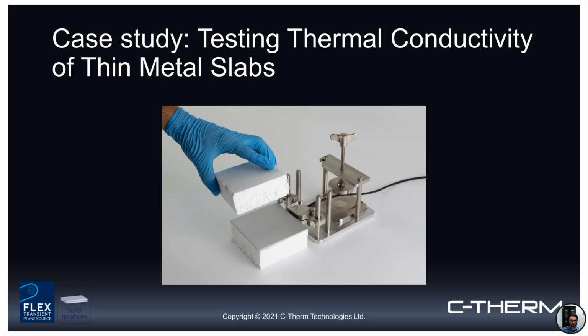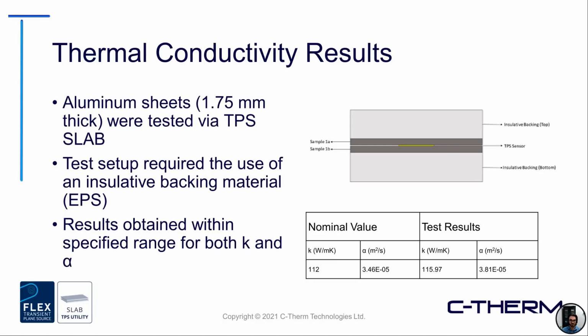And another note on one of the other advanced utilities with TPS is looking at SLAB. So Adam mentioned earlier, SLAB is really great for thinner materials, really metallic sheets as an example, or an emerging market that is really great for this measurement technique. Essentially with SLAB, it follows the same measurement principles, but you get a slight difference with the thickness requirement. So in this example, we were testing some aluminum sheets, about 1.75 millimeters in thickness.